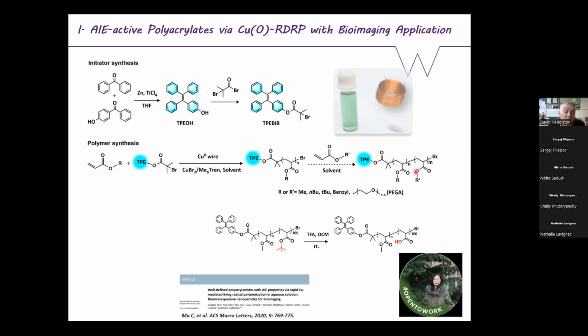We make block copolymers depending upon what we want to do, so we can self-assemble that with the emissive group on the outside. It was first published with polyacrylamides for bioimaging, actually. Essentially, if you could persuade the molecule to aggregate in a biological setting, then immediately it just lights up, right? And if it's freely dissolved, it's not lit up. So with polyNIPAM, if you can get it to precipitate, once it's precipitated, it lights up. If it's not precipitated, it doesn't light up. It's a really nice switch, and the emission is really, very bright.